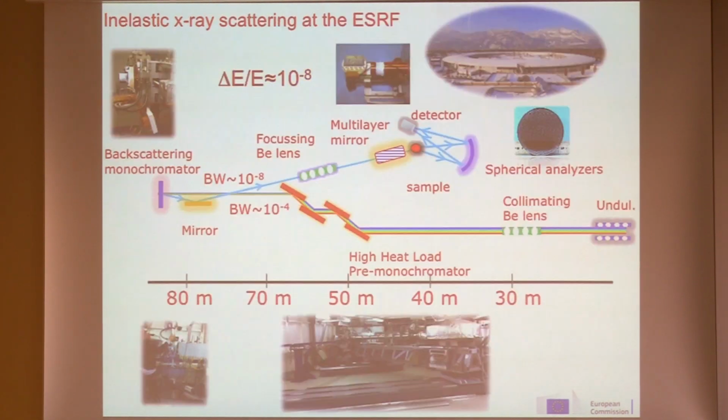Anyway, the lattice dynamics in NpO2 was studied more recently using inelastic X-ray scattering at the ESRF. With this technique, you can afford measurements on samples with very small size. On UO2, we used a sample of 10 micron size. So for this machine, our NpO2 crystal was huge. You see the machine is very long. This is a picture just of the secondary spectrometer, this part here.